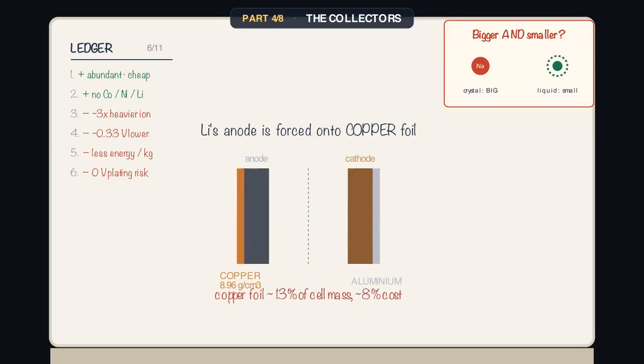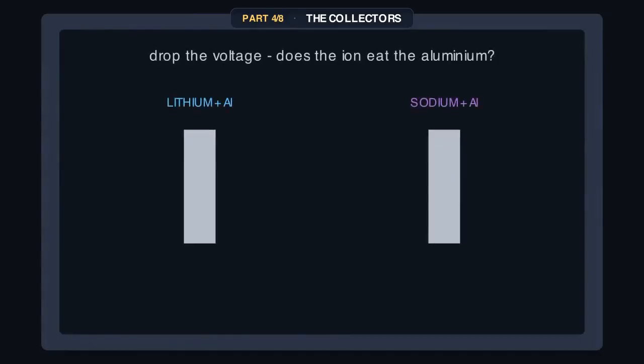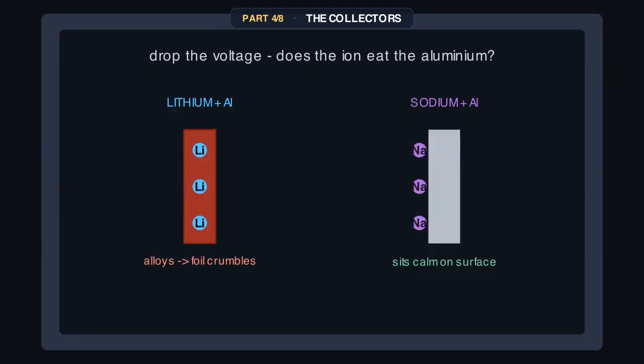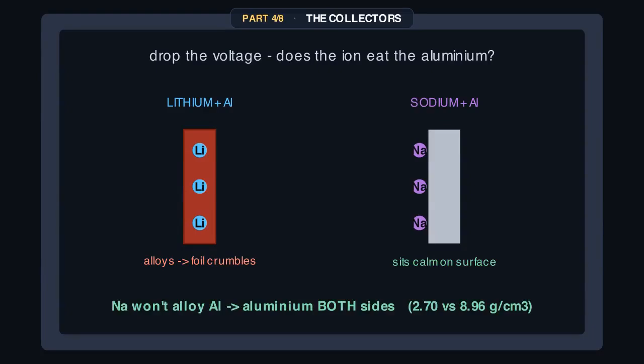That's dead weight we'd love to drop. But sodium doesn't alloy with aluminium. Watch. Drop the voltage, and lithium fuses into the aluminium and crumbles it while sodium just sits calmly on the surface, untouched. So sodium lets us use cheap, light aluminium on both sides of the cell. Aluminium is a third the density of copper, 2.7 against nearly 9, and several times cheaper. We just deleted the copper. Lighter, cheaper cell from one quirk of chemistry.